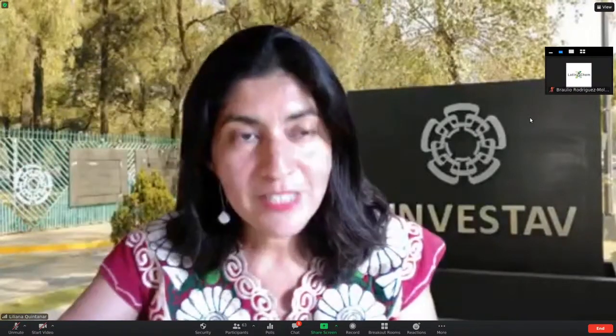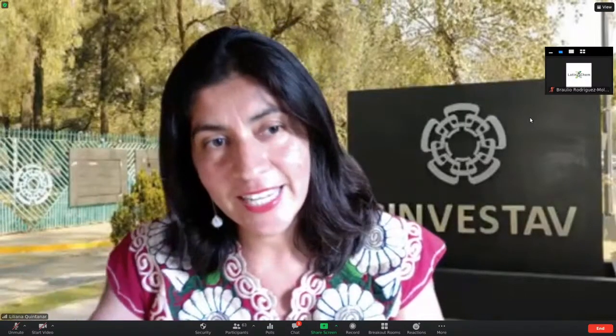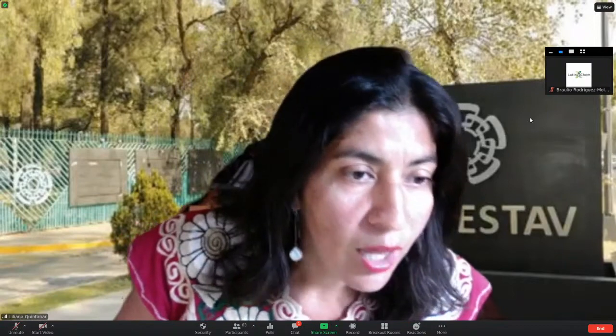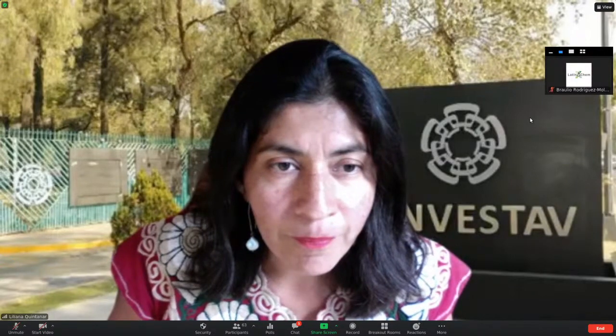Yeah, it looks like that because you saw the drop in the turbidity assay and then it increased again. Maybe I can quickly show. But it's not really because, so if you can see it here, perhaps, Jorge, is that what you were thinking, that it's seeding? This trace comes from here. We add the copper and then that immediately causes aggregation. You don't even need to measure it with turbidity. You can see the solution getting turbid. And then when you add EDTA, it becomes clear. And soon after, without doing anything, just following it in the plate reader, you can see an increase in the